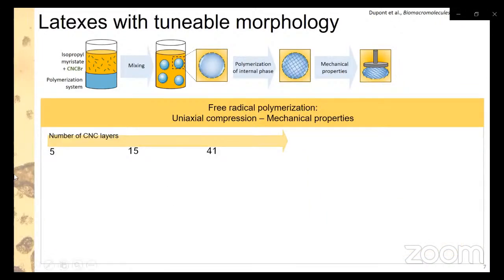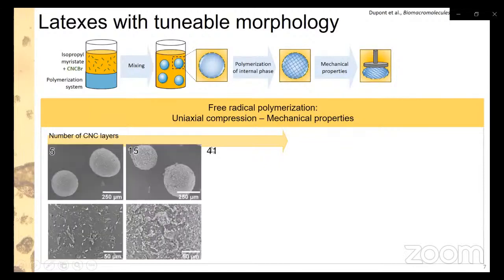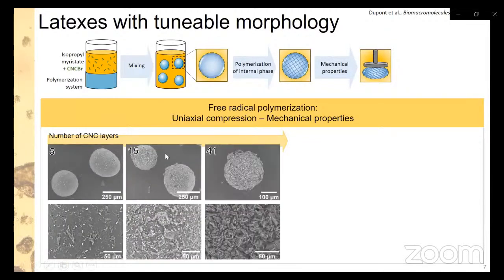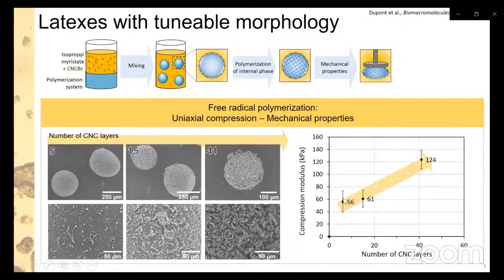So we were also able to vary the number of CNC layers around each droplet from 5 to 40. As we can see here by SEM, the more dense the coverage becomes, the more aggregated the surface is. So you can see that here the surface is more dense. And by measuring the compressive modulus, what we could see is that by increasing the number of CNC layers, we also increase the mechanical properties of these latexes.